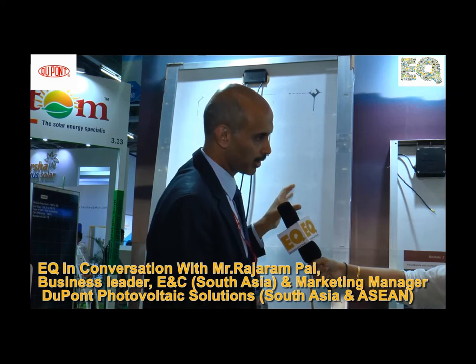DuPont conducts a lot of field audits, where our technical team takes its equipment and goes out into solar projects that have been installed for some time. We have shown two samples here. One is a PET-based backsheet picked up from an installation in Tibet that has spent only nine years in the field. If you look at it, it has already started to chalk — it has become so thin you can almost see the back of the cells, which is very dangerous. Power generation has gone down, and all the elements of weather have started hitting the cells. If electricity starts coming out, it is potentially catastrophic because this is DC current, and there is a great possibility of it causing bodily harm.